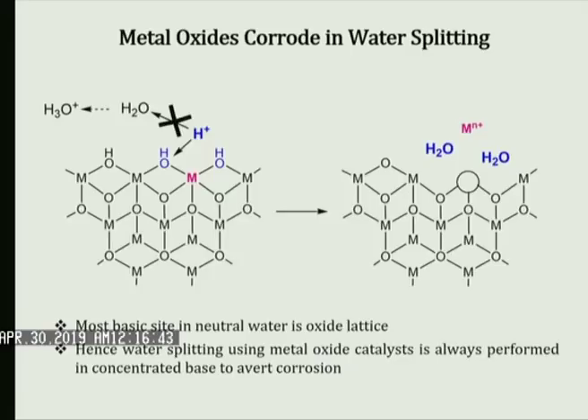If you have metals, metals can go to oxides, and when you have an oxide, if I split water, I make O2, I have protons left behind. And the protons will react with the oxide, and if you have two more protons that add to oxygen, you make water, and then the oxide starts decomposing, and then the metal ions dissolve in solution. So that is what happens in any water splitting system with oxide.